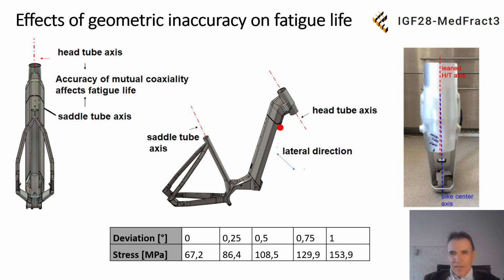When the geometry is not perfect, in the simulation it is possible to obtain the results documented in the table down here. When the deviation is zero, the geometry is perfect, and the maximum stress in the most loaded points of this frame is 67 megapascal. When the non-parallelism between these two axes is 1 degree, the maximum stress in the same cross-section increases 2 times, to 154 megapascal. But this is additional loading which is not considered in the standards assessment. The reality is that this inaccuracy is present in the real frame, and it is necessary to consider it in the fatigue lifetime assessment.